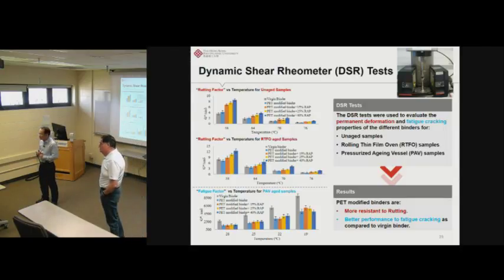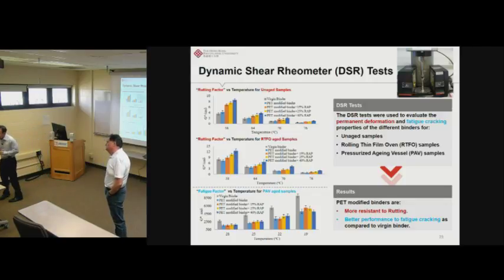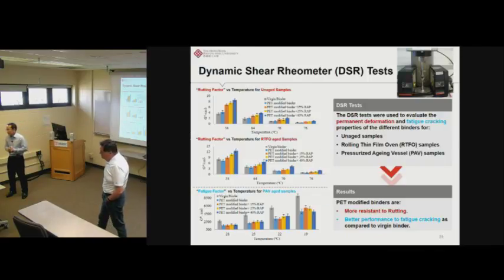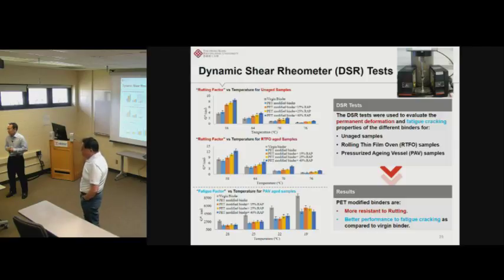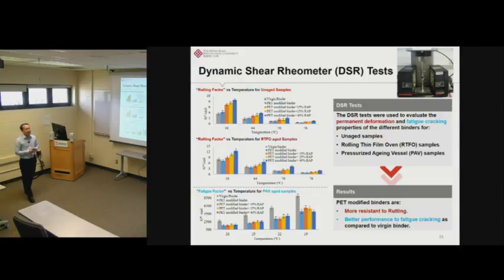But the thresholds will change, for example, I'm not sure if you're using Superpave. Adding PET, first of all, whether it changes the grade or not. These thresholds will change, because let's say it's initially a 64-22, but when you add PET, let's say it stiffens the binder, it becomes 70-22. Yes. So in that case, the rutting value will be tested at 70 degrees Celsius, and the threshold will be at a different temperature to be matched compared to 64. Yeah, that's what I said. It's temperature and load. So if that's the case, you will switch it to a different temperature.